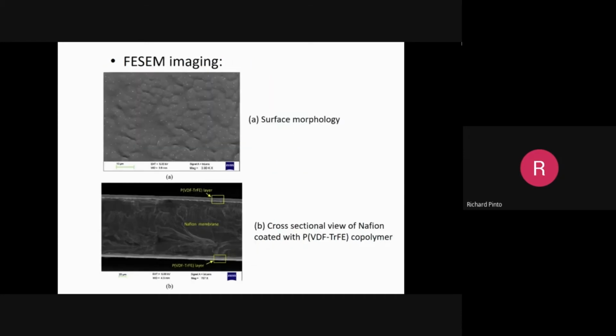Now these are some details of surface morphology, the SEM pictures of the surface of the coated membrane. Cross-section view of the Nafion coated with PVDF-TrFE. You see the 1 micron thick coating here. A beautiful picture. This work was done at IIT Madras actually. He did an INUP program, Indian Nanoelectronics Users Programme. Arjun is a student there. He worked there in 2018 and 2019. This is a very nice picture showing the cross-section, the thick membrane, and the 1 micron, 10 micron thick PVDF-TrFE layer.